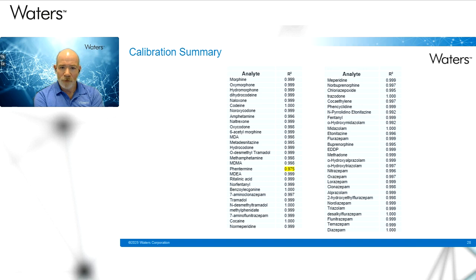Other than that, we had very consistent curves for all of the other analytes. As you see, very, very consistent QC results as well. One thing that we did notice with the hair samples is, not surprisingly, they tended to be much more affected by matrix effects. For example, meaning that if we did not have a deuterated internal standard, we saw much more variability than I would typically see in a plasma or a urine sample. So that was the one takeaway: the more deuterated or labeled internal standards you have, probably the easier your analysis will be.